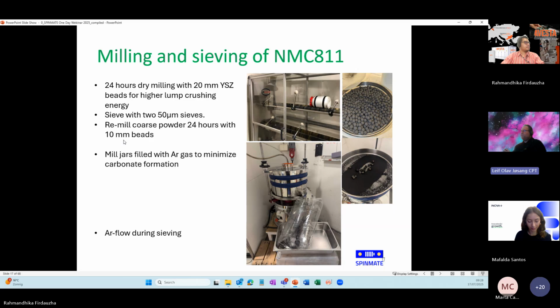And we also filled the mill jars with argon gas to at least reduce contact with moisture. And we also used argon flow during sieving, where you can see there's a tube going into the orange lid on top of the sieve there, and you can also see that the collection bag is inflated.